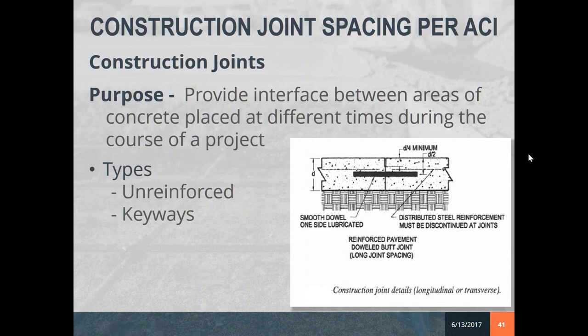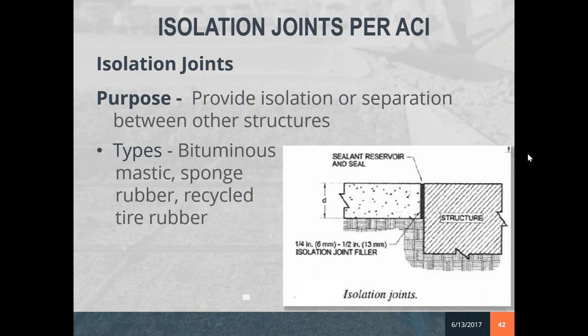Again, we have our load transfer, our construction joints. Those are very important in order to transfer the load when you do have a cold joint between construction joints, when you've stopped and started from one pour to another, maybe a day-to-day pouring process or operation. And we also have isolation joints, and sometimes you want structures to move uniformly. Sometimes we want to separate them, as with a sidewalk that's right up to a building, where you don't want that to be moved uniformly with it. Sometimes we don't, so an isolation joint is another joint that is used in order to allow the concrete to move, reduce the amount of cracking, and function appropriately.